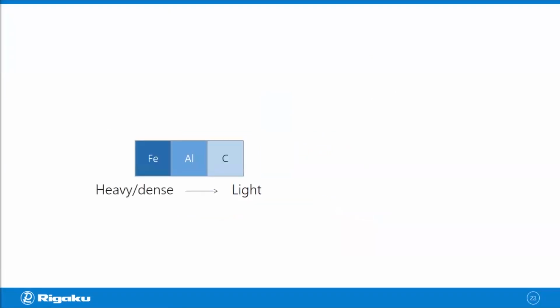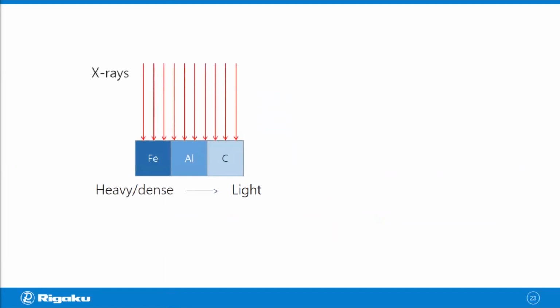For example, if you have a plate that's made of iron, aluminum, and carbon, and if you put X-rays through it, and let's say you put a film underneath, you're going to see something like this. So iron is dense or heavy, so it absorbs a lot of X-rays, and as a result, the film doesn't get burnt much. Carbon, on the other hand, is very light, so it does not absorb X-rays that much. So the film, as a result, gets burned quite a bit. Aluminum, density-wise, is somewhere in between. So the gray level you see on the film is also somewhere in between. So you can see that the X-ray absorption rate is density dependent.